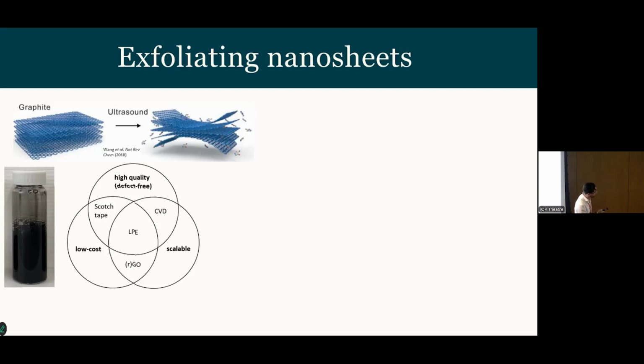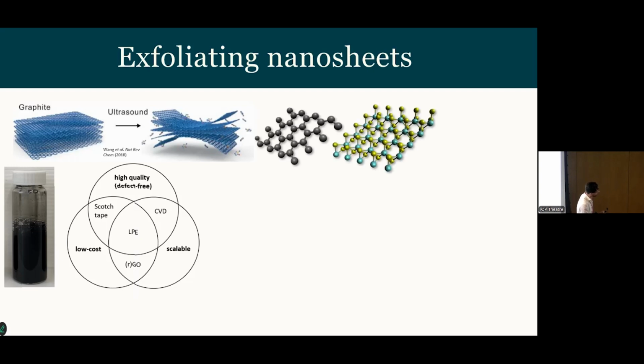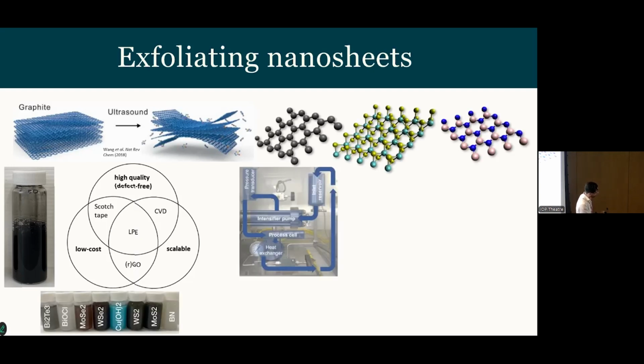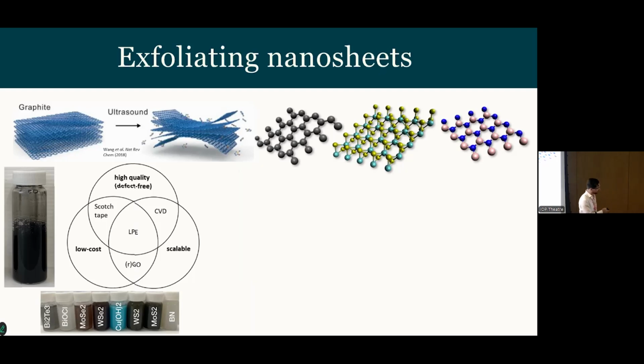So it's similar to the Scotch tape method in that sense. But it's more scalable and much lower cost than chemical vapor deposition or reduction of graphene oxide, or even potentially electrochemical exfoliation, which is a new technique developed in this area. So we can do it with graphene, but we can also do it with molybdenum disulfide, boron nitride, or any one of a range of materials that we exfoliate in our lab.